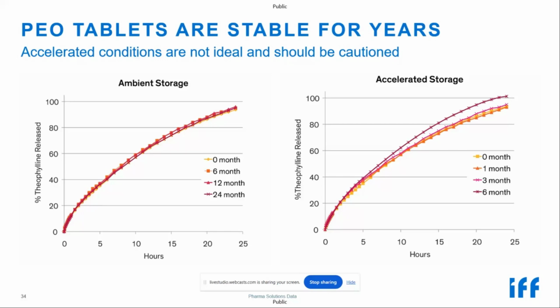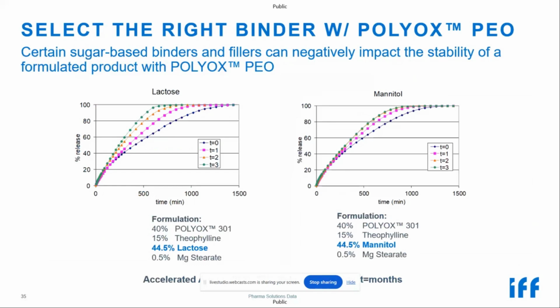The other thing I take away from this data is that 6-month accelerated storage condition is not indicative of, say, even a 2-year storage condition. You have to do a really good model to understand how accelerated storage is related to ambient storage because those conditions are so harsh to POLYOX. It's just better to go with ambient storage to understand the true stability nature of the formulation. That being said, accelerated storage can be very useful to push a formulation to understand if there are potentially any instability issues within a formulation.